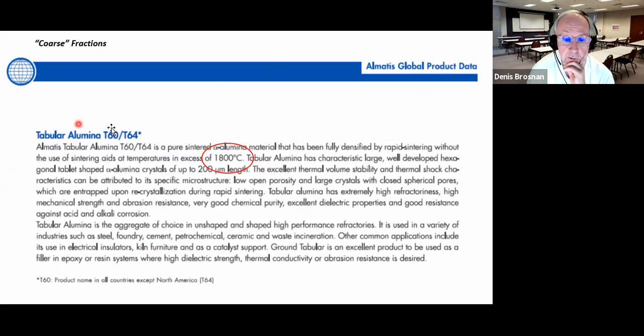Now, tabular alumina is sold by Almatis in the grades T60, T64. I'm not biasing my comments to the company Almatis, but to my knowledge, they're the global leader in producing aluminum oxide. And here in their data sheet, they say that it's calcined to 1800 degrees C. That's a pretty high temperature, and typically in a rotary kiln, so sometimes it's challenging to measure temperature there, but nevertheless, it's super high calcined. Calcination temperatures render it what the old guys would call dead burnt. It doesn't change very much. It's not very reactive, but certainly in refractories that can be useful for strength, slag corrosion, and high temperature load bearing capability.